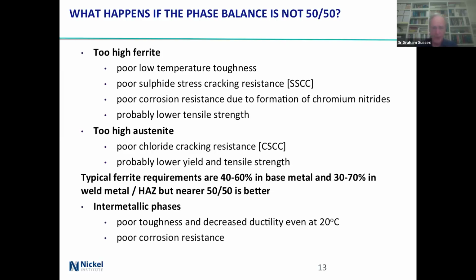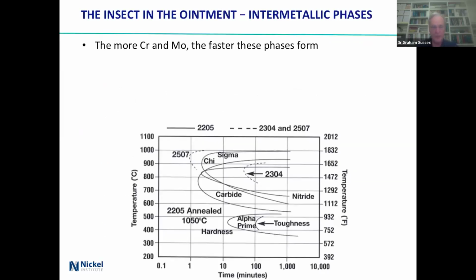One of the big problems, particularly with the higher alloys, is intermetallic phases. So instead of getting nice oxides on the surface, you wind up with iron, chromium, sometimes moly, and you'll lose ductility even at 20 degrees C. You'll also get pretty poor corrosion resistance. The fly in the ointment, I was going to say insect in the ointment, but I decided not to, but I did. So the more chrome and moly, the faster these phases are going to form. Here we're looking at temperatures, and I hope you can see enough of that, looking at various areas. So we've got 2205 there with the solid lines, 2507 super duplex, and then one of the lean ones, 2304, with the dotted lines, and the precipitates that happen.